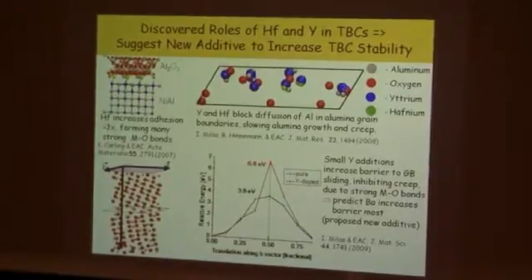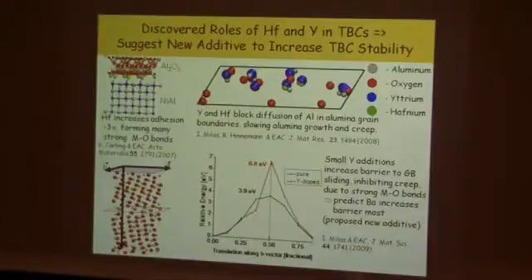We then looked at, this is another thing we can do on the computer. We could go through and basically look at most of the periodic table and elements that we thought really love oxygen and figure out which one is the best one to add that would help slow down this growth. And we discovered that barium, which is a very big metal atom, which loves oxygen, increases this barrier to sliding the most, which ends up leading to failure. And so that's the new additive that we've proposed in this patent to add to this metal coating. And so hopefully this will be a way to improve some of the efficiency of airplanes.